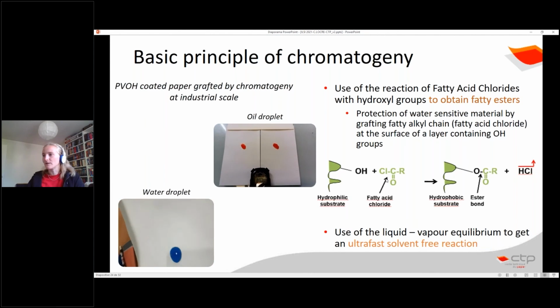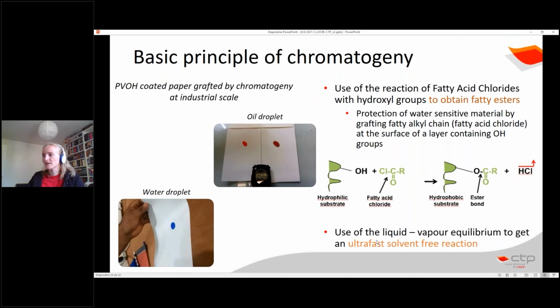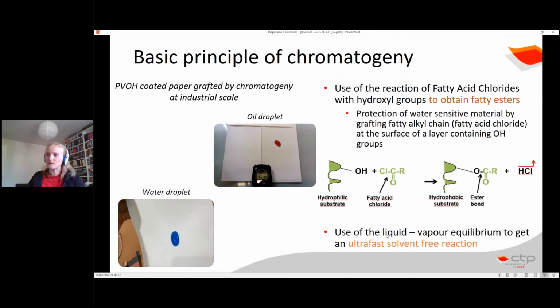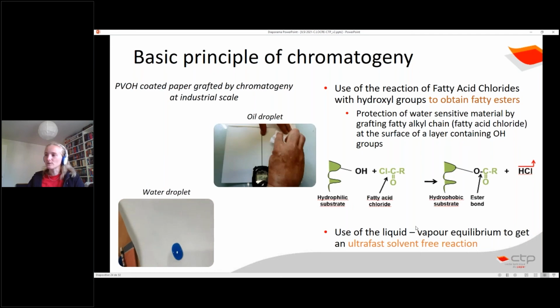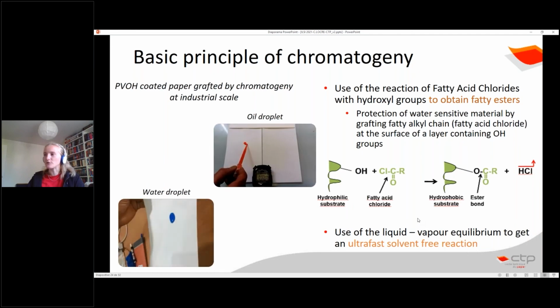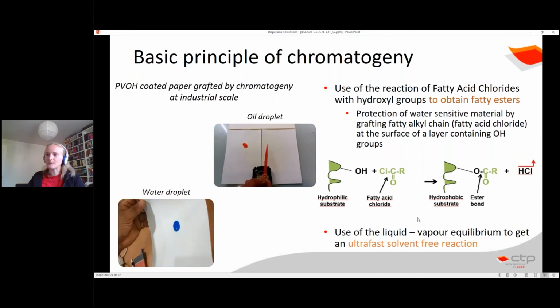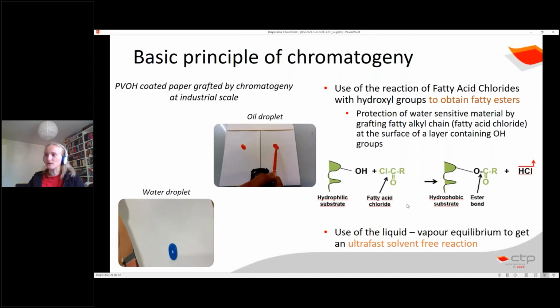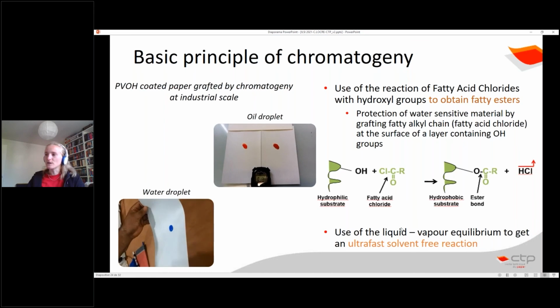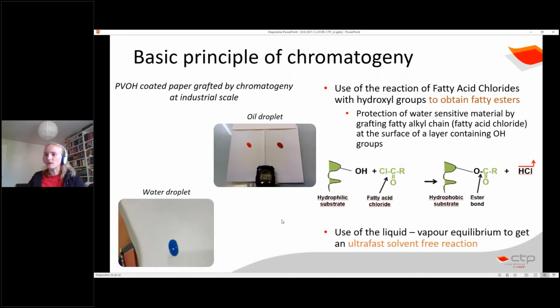Here you can see that the fatty acid chloride reacts with the hydroxyl group, and that an ester bond is formed with the material. And in order to do that, the fatty acid chloride is deposited as a liquid on the material in the range of 0.2 to 0.5 gram per square meter, so a really very, very low amount of fatty acid chloride, which is enough to get this ultra-fast solvent-free reaction and hydrophobize the paper.